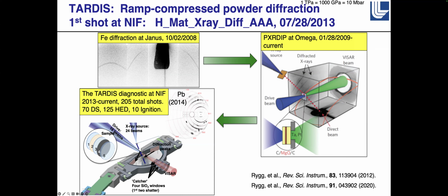And it turned out the reason for that is because when you make these X-rays, you get a lot of bremsstrahlung. So you get a lot of hot electrons that come out of this X-ray source and fly around. They can hit the sample. They can hit the backlighter itself. They can hit the pinhole. They basically bathe everything in high energy X-rays.